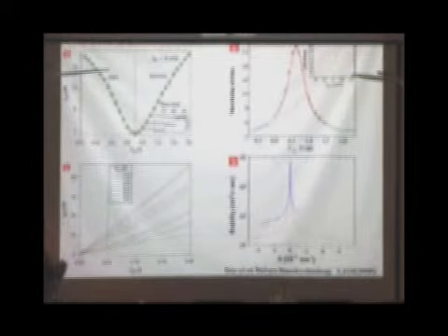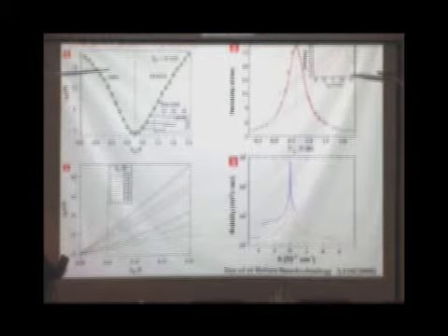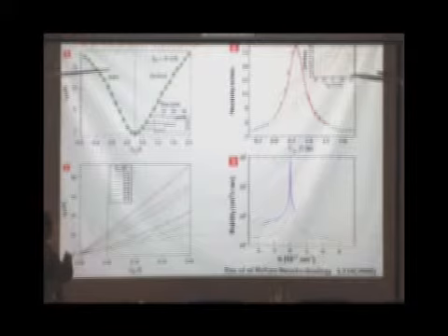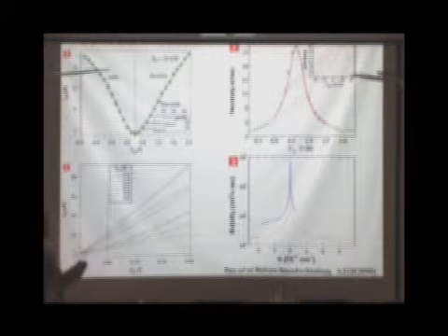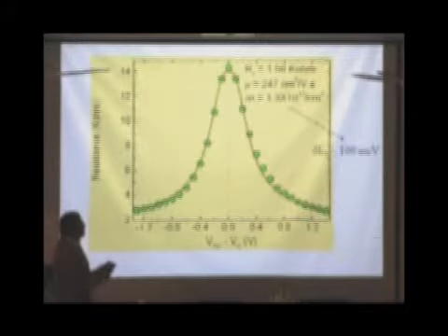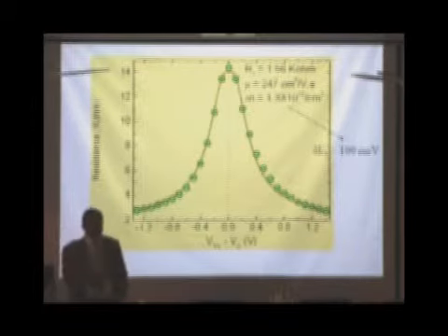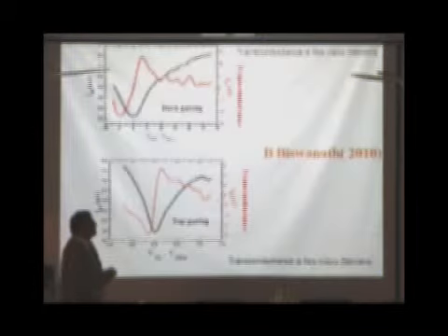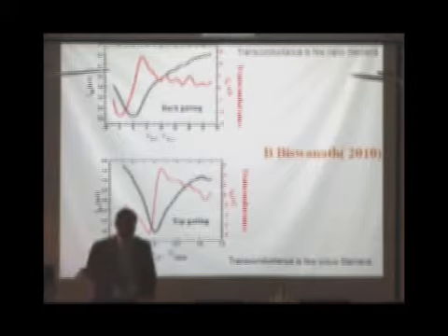Once you do this, you can plot source drain current as a function of gate voltage. Please see, it is not 100 volt, it is minus 1 volt to plus 1 volt. This is the whole doping, these are the electrodes. And you can show what is the resistivity of this device. You can fit to a model. We do that, and you can show that this device at room temperature had about 247 centimeters square per volt second. So this device has some uniqueness.